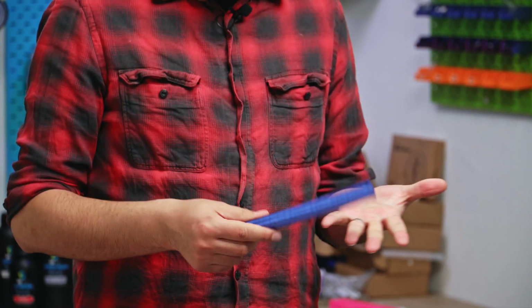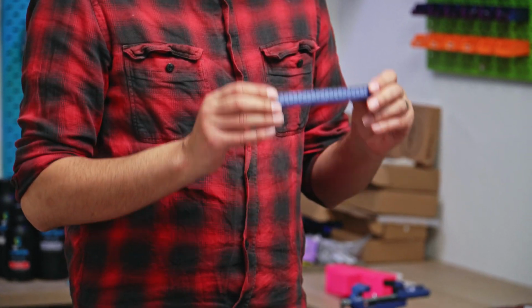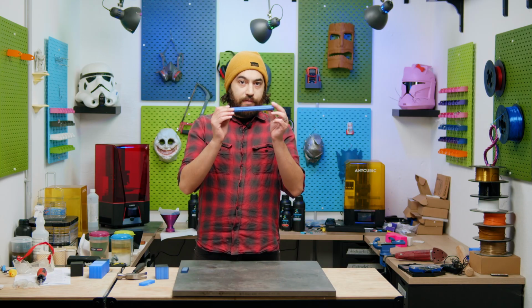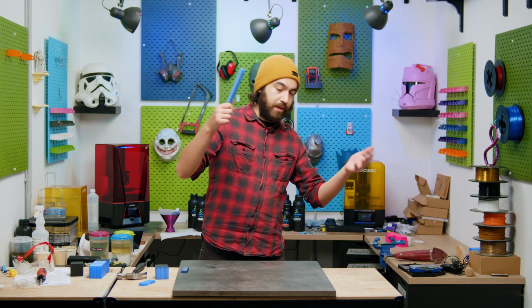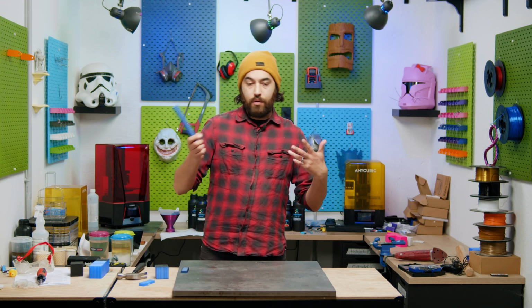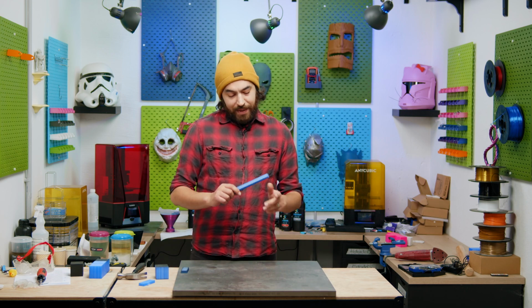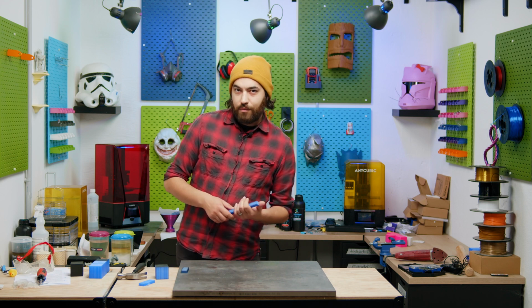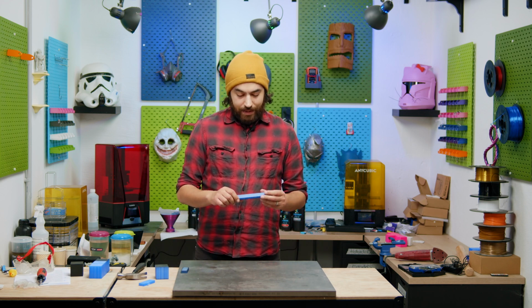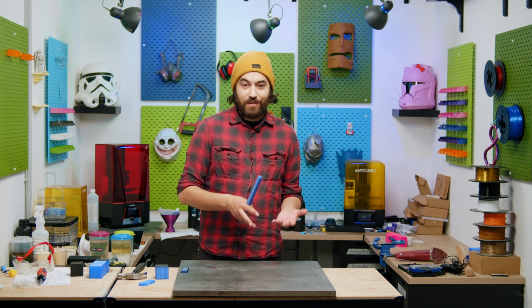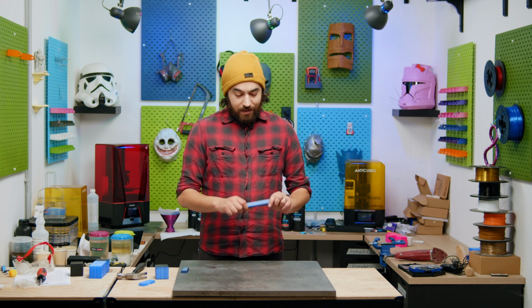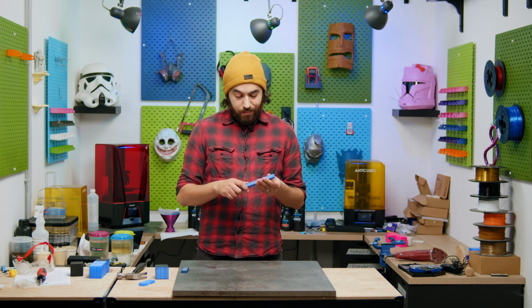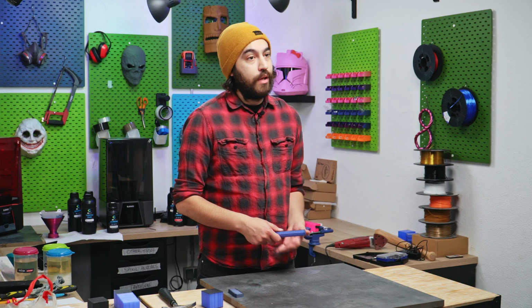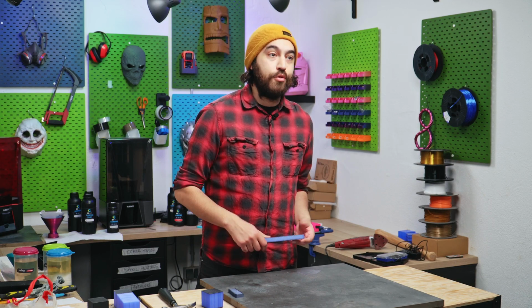Now, these were printed simply by using a color change command in Prusa Slicer and then manually changing the spool when it paused. By the way, if you're wondering why I did this manually and not with an MMU or a palette or a Bambu Lab AMS, it's because TPU doesn't really play well with those kinds of devices. The unload and load process is just a nightmare for soft filaments. So you can do it manually, but the best way to do it would be with a straight up dual extruder printer, or as Joel used, a Prusa XL or other tool changing printer.